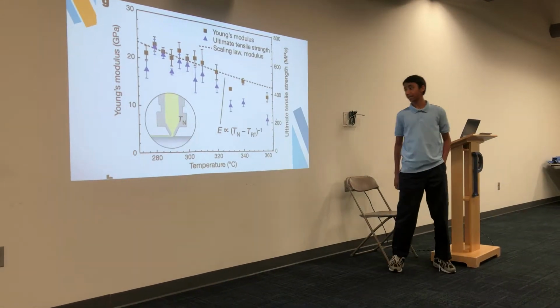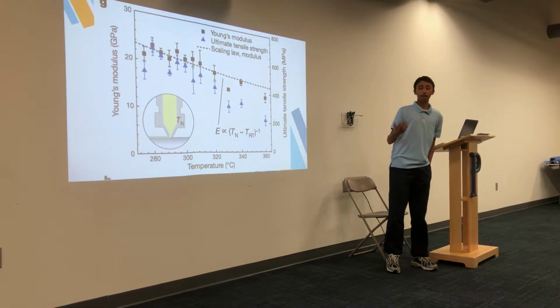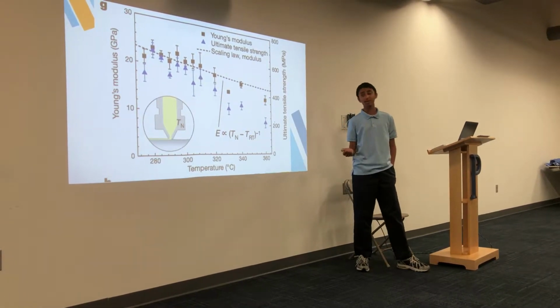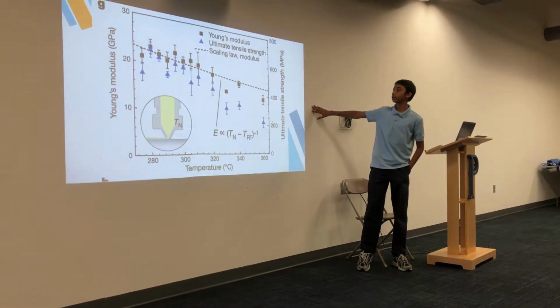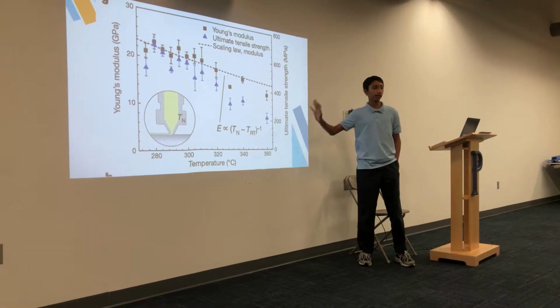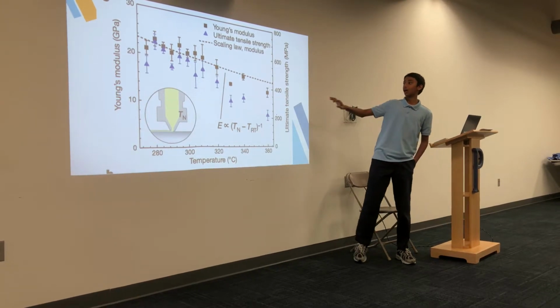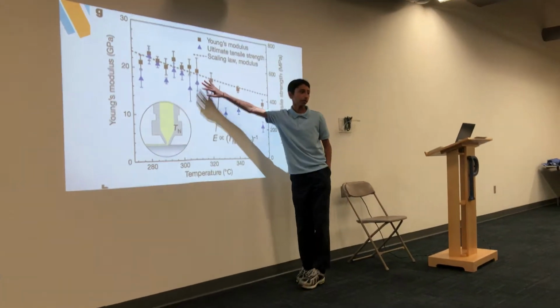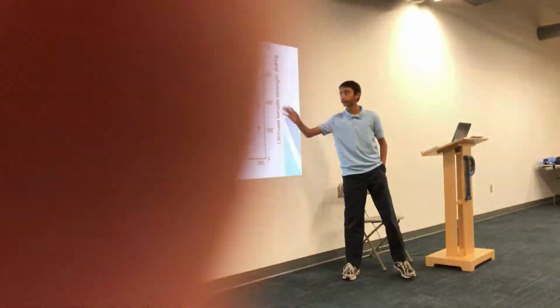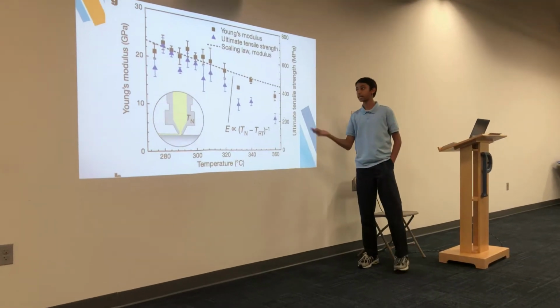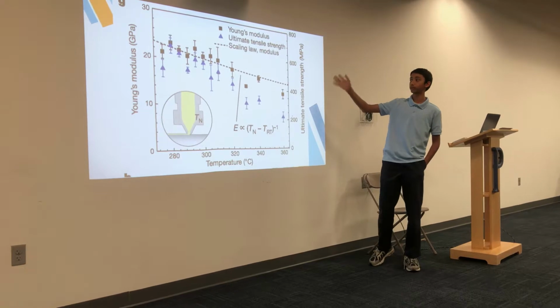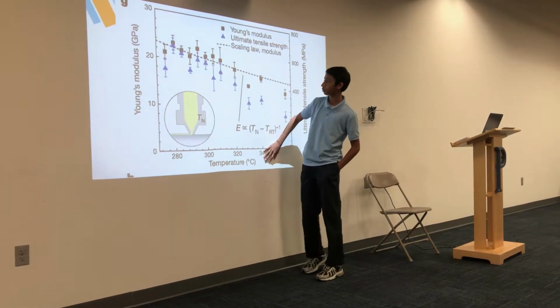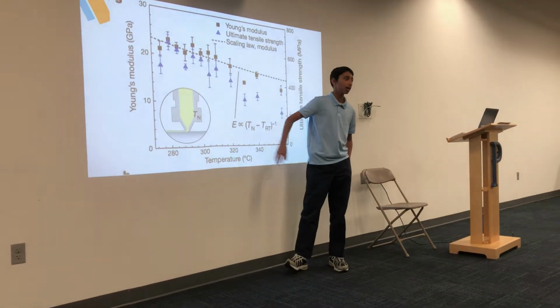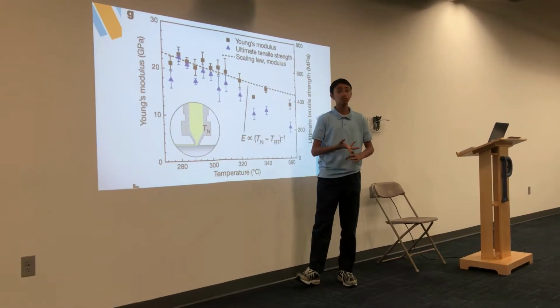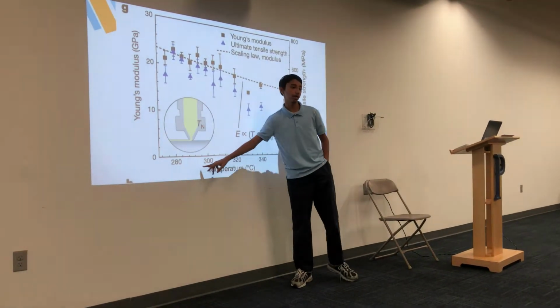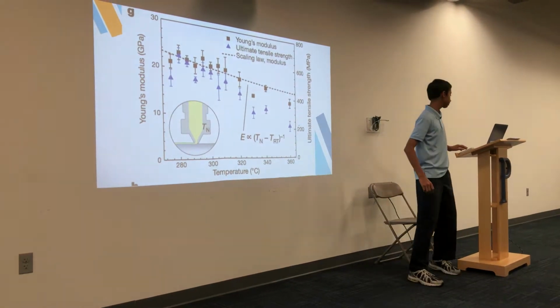So the second factor they look at is the temperature of how hot the filament coming out of the extruder is going to be. You can see that here the graph is a little less easy to decipher. It's kind of a mess over here, where the data is fairly strewn about, and it's difficult to come to any clear conclusions about where the highest point is. But if you were trying to figure out the best compromise of the best temperature, where you get the most stiffness and the most strength, it would probably be somewhere in this 280 to 300 degrees Celsius range.